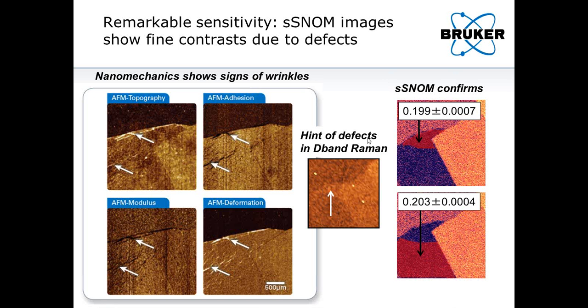And if we now perform some statistics on the IR SNOM images for that region, we see that taking the average signal over the region that seems to light up in the D-band Raman image, we see a clear difference—roughly a 2% difference. So it's an easily detectable 2% contrast that is caused by defects in this outer portion of the single-layer graphene, and those defects are likely connected to the wrinkles that we observed with the nanomechanical measurements.